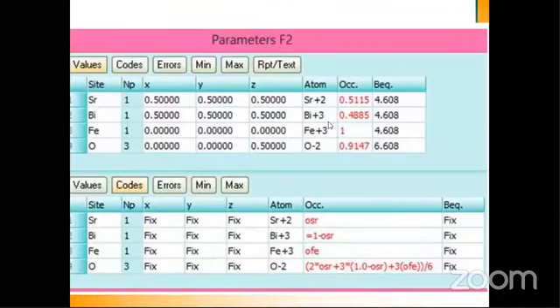For example, in one of the research projects with Professor Khurshid Hasnan, I replaced strontium with bismuth, and they were 50-50. If you refine those particular atomic positions, then you can say exactly how much bismuth is there inside the strontium. These are the refinement end results.